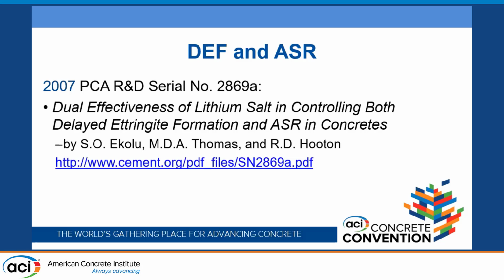But analyzing the leaching properties of the lithium and alkali levels of the mortars, it was found that you need a lot of lithium to get the job done. So this was an important report for us.